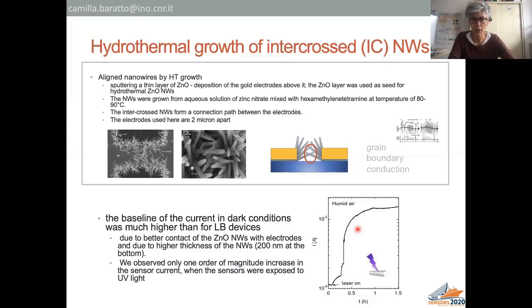If we go to the alternative technique we developed during this collaboration, we decided to prepare nanowires by hydrothermal growth using a patterned substrate where the zinc oxide thin film was deposited below the contacts as a seed substrate to generate the nanowire growth. And as you see from this low magnification image, the nanowires grow only at the border of the contacts, and the nanowires crossing the two contacts, if they are long enough, generate conduction.